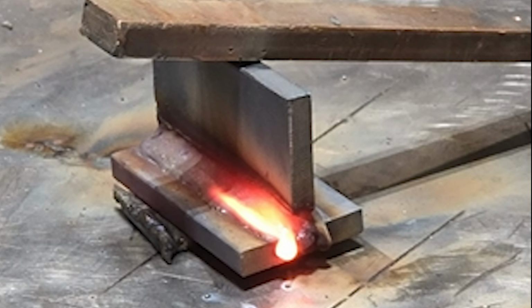To give you an idea of how hot that was, this is what it looked like immediately after welding it. And keep in mind, this was at 125 amps. So the whole thing was like bright red, and the end half, so the second half, was literally almost still molten when it was done. And it was kind of funny because the back side of this was glowing almost as much as this is that you see here, which would make you believe that you're penetrating right through that, you're about to melt through the whole steel. But when we look at the cut and etch, it tells a completely different story. And I think you're going to definitely like this one. So let's look at it.